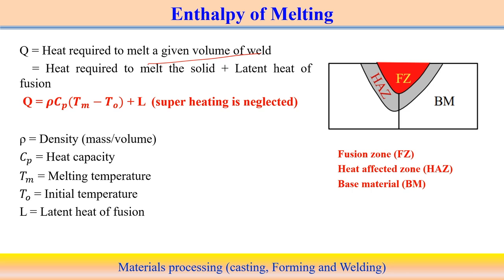We can estimate the total heat as Q = ρ × Cp × (Tm − T0) + L, where ρ is density, Cp is specific heat, Tm is the melting point temperature, T0 is the initial or ambient temperature, and L is the latent heat required to change the phase from solid to liquid. Counting both components gives the total amount of heat energy required to melt the substrate material, which is called the enthalpy of melting.